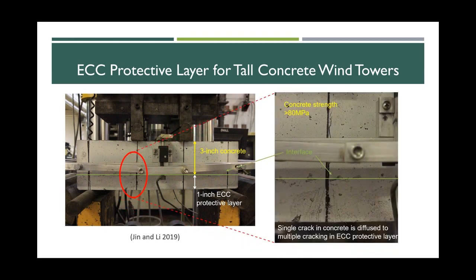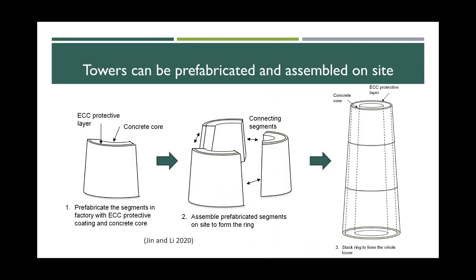And in this case, again, as I showed before, the major crack in concrete can be arrested, and a single crack in concrete is diffused into multiple cracks. Multiple cracking is fine, and it protects the inside concrete from aggressive chemicals and other things. And these concrete towers can also be prefabricated and assembled on site. With this ECC protective layer, the concrete core can be made in prefabrication manufacture, and then the segments are connected and stacked on each other on site.